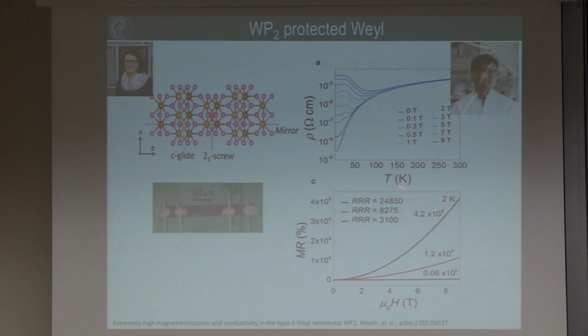So this material has a giant RRR value, therefore we were very happy. But what made us especially suspicious was that we had a resistivity even smaller than the resistivity which Andy Mackenzie found for palladium cobalt O2, which made him also very unhappy. So he wanted to see our data. He reproduced our data, he remeasured our data. Okay, so it's a more common feature.